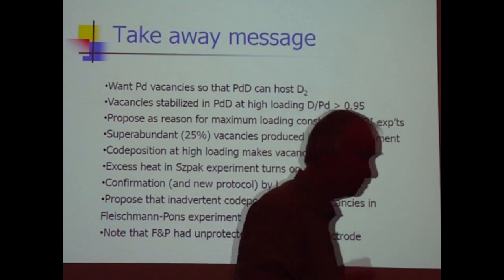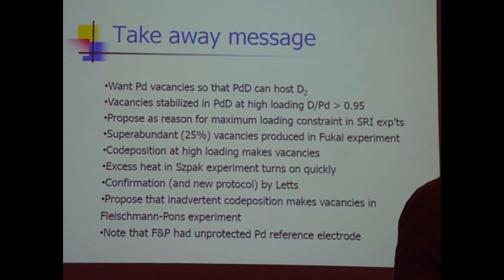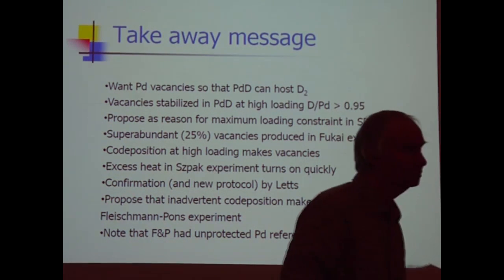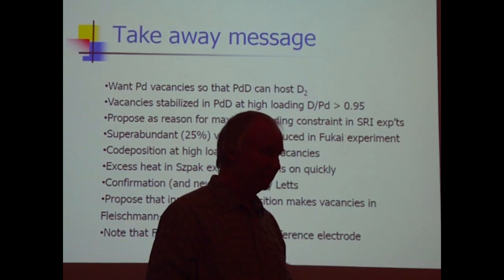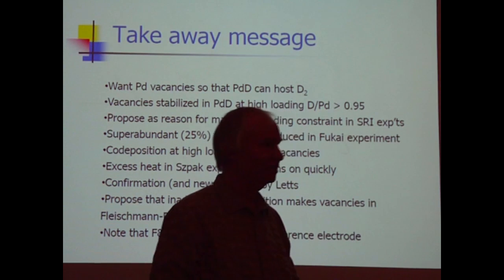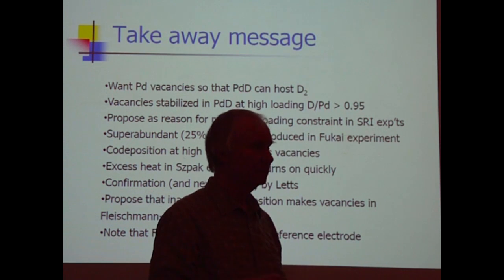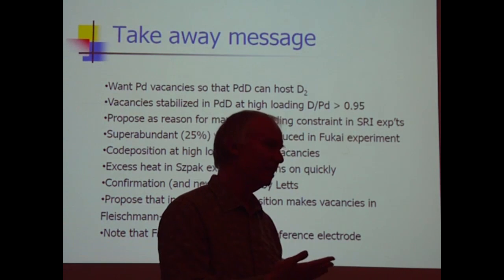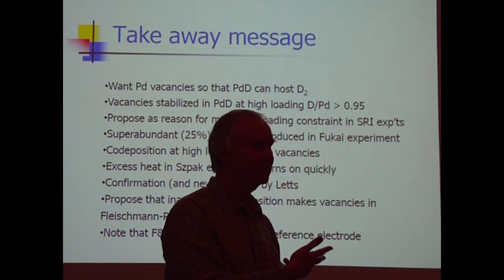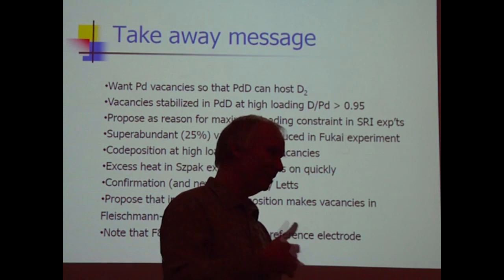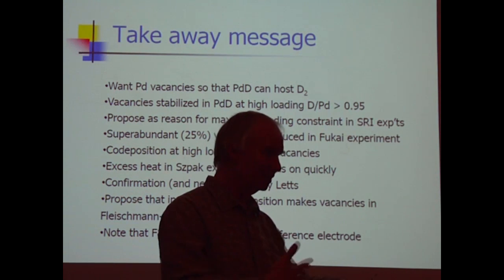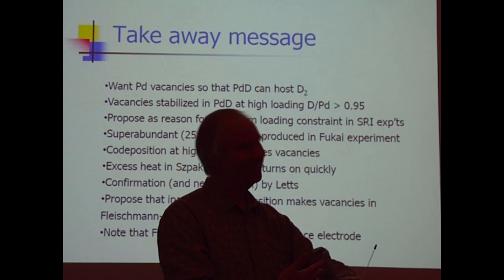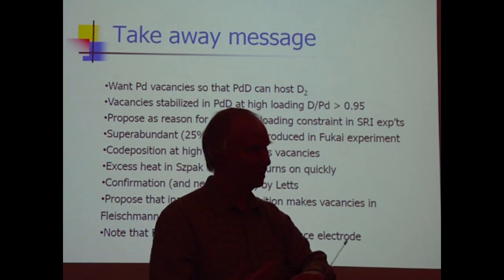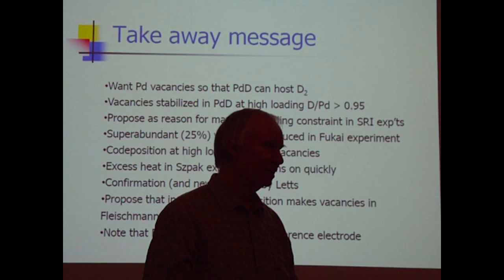I have a question. Is there a way to prepare the cathode other than using electrochemistry, like by sputtering? As we talked about before, certainly sputtering could be done, but sputtering by itself wouldn't be expected to make lots of monovacancies unless you co-sputtered hydrogen or deuterium under conditions where it could be kept in the lattice to get the high loading in order to stabilize the vacancies. So I don't think so.